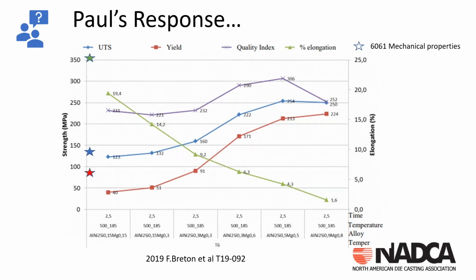So how do these compare to 6061 alloy? So 6061, and this is now the mechanical properties. These three stars represent those mechanical properties. So this is the elongation. The elongation is right around 25% for 6061. It's around 125 to 130 ultimate tensile, and it's just under 100 megapascals for yield.